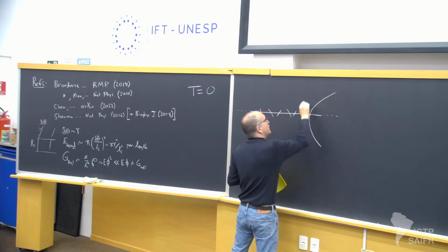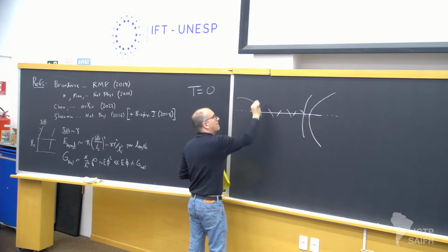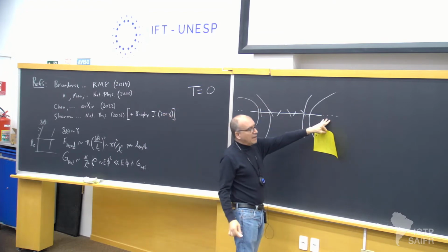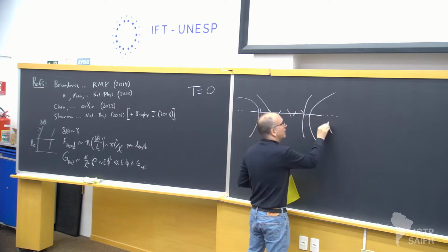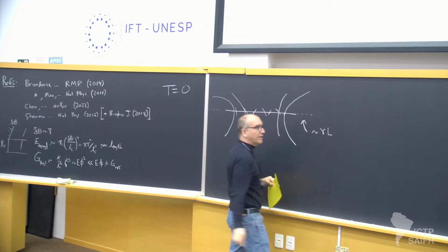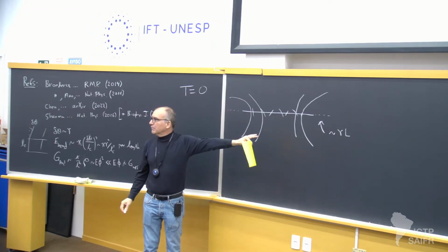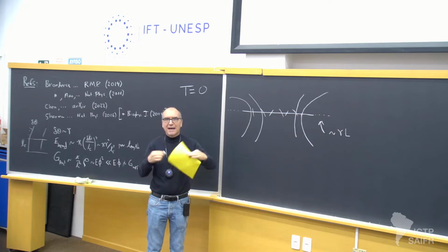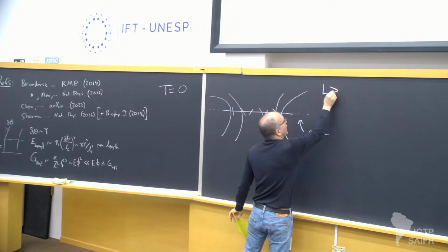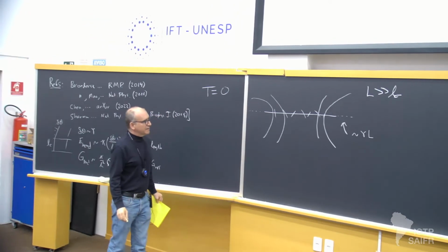Well, they start to get pretty radically bent, right? In fact, the amount of contraction here is going to scale as the strain imposed and the length of the fiber. So L is going to be my symbol for the molecular weight or length of the fiber, and you should imagine that this argument is really for L much greater than the mesh size or cross-link distance.